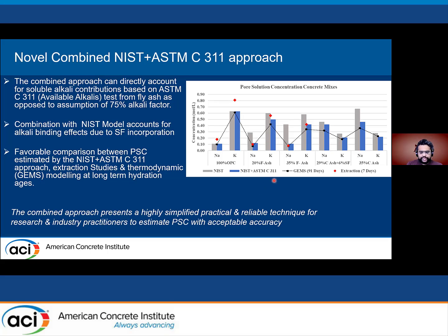The thing is, the thermodynamic model is a highly reliable method, but it also presents a very complicated technique for industry practitioners. So here, the important aspect is the combined NIST and ASTM C311 approach. The focus is that it presents a highly simplified approach and also a reliable technique for both research and industry practitioners. And it does allow us to estimate the PSC with the SCMs with a very high level of reliability.